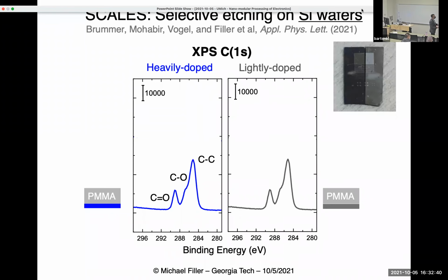Okay, so what do you get? We do a lot of studies on planar wafers because of characterization techniques that only exist for planar things. It's actually really hard to characterize nanoscale objects with a great bit of detail. So we start with planar systems. This is a wafer that we've patterned with heavily doped and lightly doped regions. And what you're seeing here are XPS, photoelectron spectroscopy, spectra of PMMA. So these peaks are characteristic of PMMA structure. Basically saying, yes, you have PMMA on the surface for both the heavily doped and lightly doped surfaces.